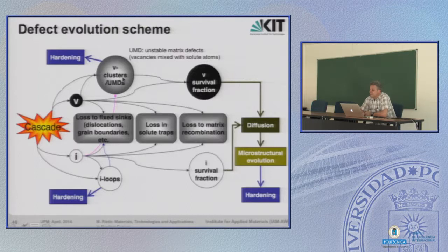And finally, the clusters, if they are big enough, they don't vanish in the crystal. And what do they cause? It's hardening. Remember the story from yesterday. If you have some defects in the matrix, then this leads to hardening because the dislocation cannot move as easily anymore. This is how these interstitial loops, dislocation loops, end up also. If they are large or big enough, they are stable, they don't go away. And what they do, they block other dislocations from movement, from gliding. So they are also a cause for hardening of the material.